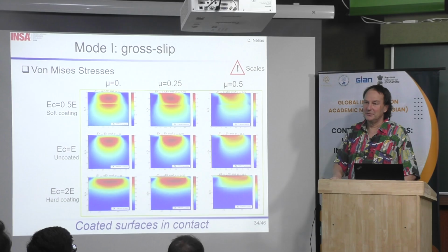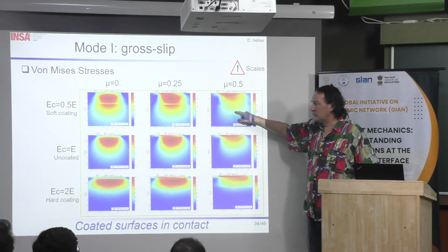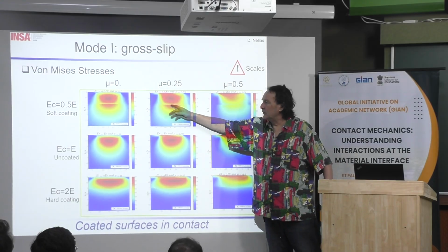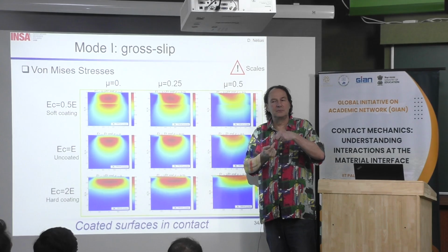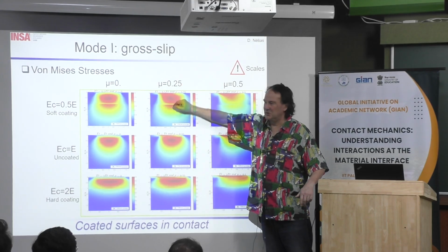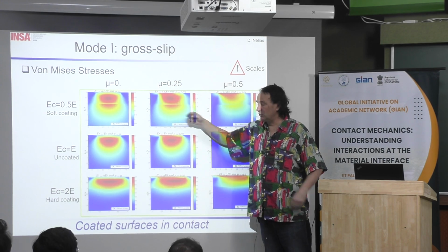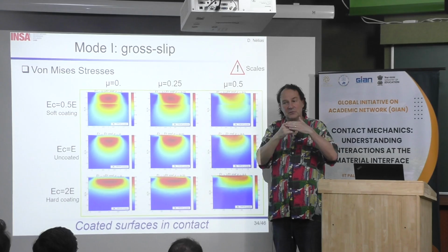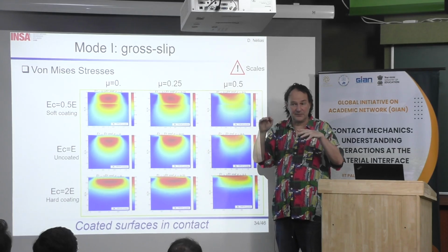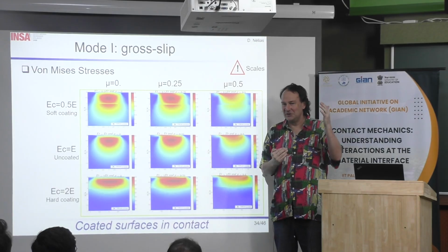This is one solution. Because here I can see that there is a lot of discontinuities. And if you calculate here, for example, of course, if you calculate the tensile stress, it should be compressive, because you have a contact, okay? Then it should be compressive, and especially because this is a normal stress. However, the shear stress should be very important. And then you may have some decohesion, or some crack that initiated that. Then, of course, you may have a very, very thick coating.